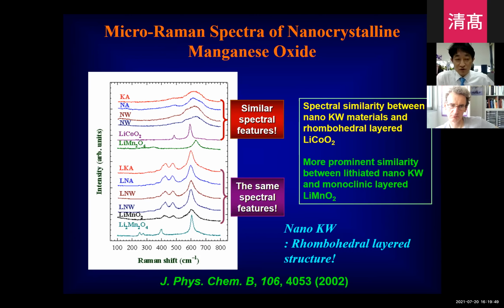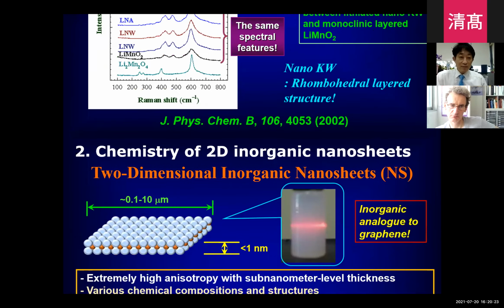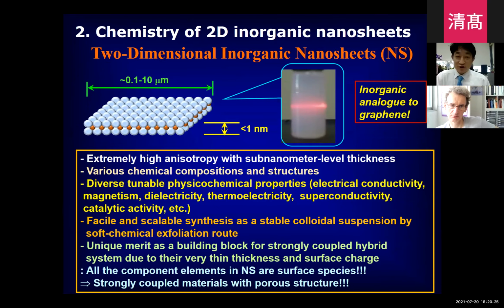The Raman spectral feature is closer to the spectral feature of LiCoO2. So if you lithiate these materials, we get much clearer information on the spectral similarity between the layered phase and this nanostructured material. So by combining EXAFS and Raman, we can determine that the local structure of nano KW corresponds to the rhombohedral layered structure. Okay, let me move to our recent research activity.